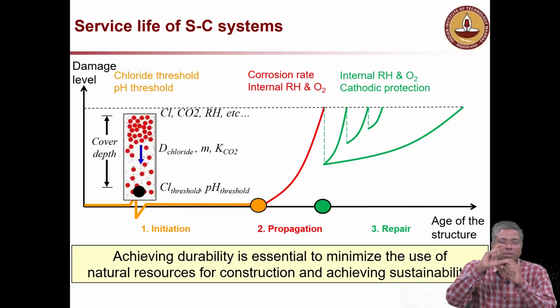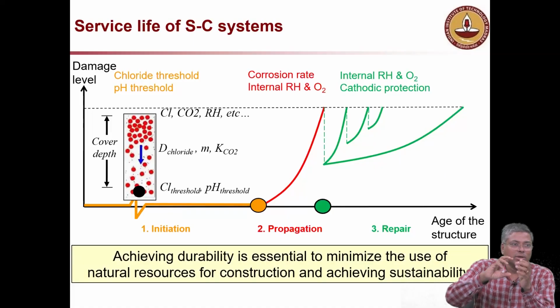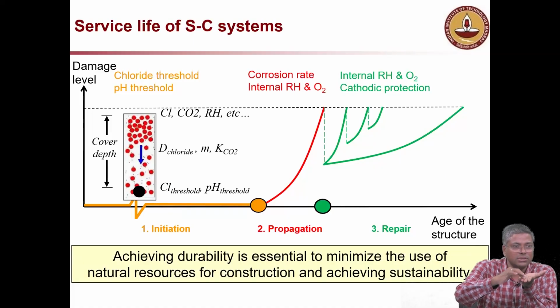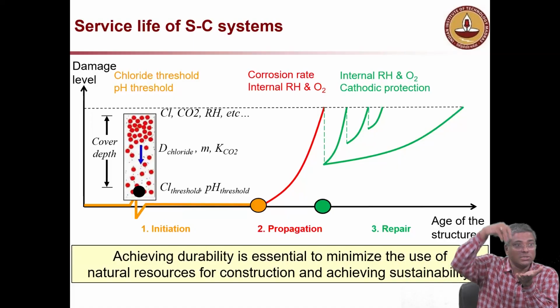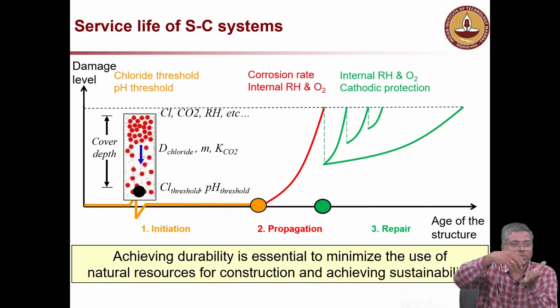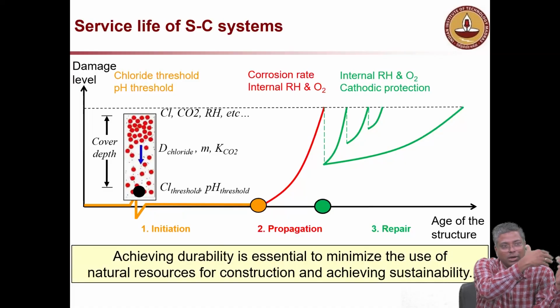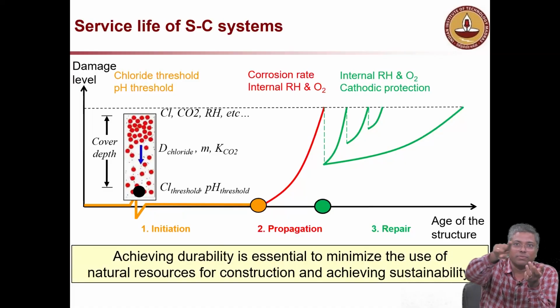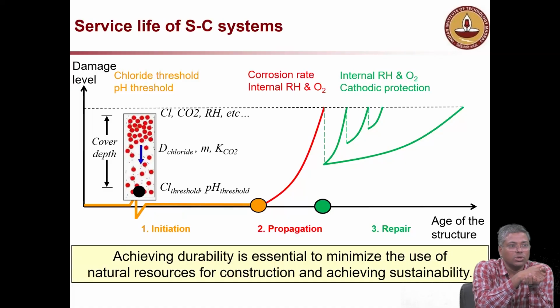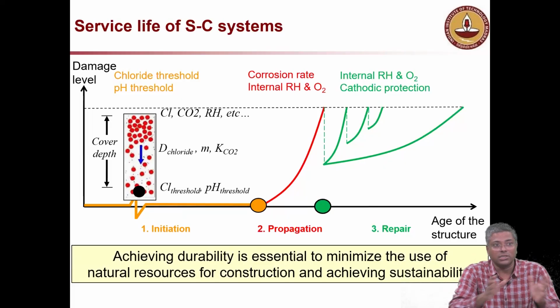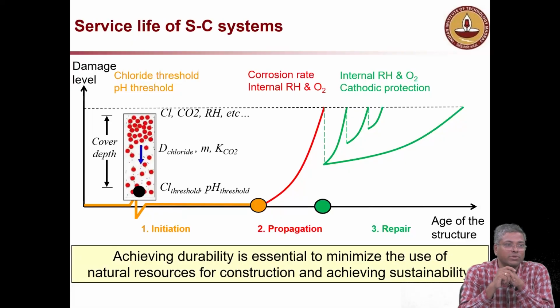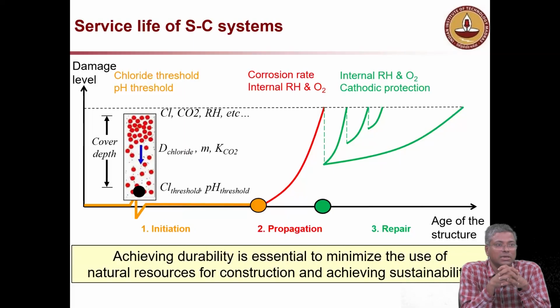See, the cover thickness is not like one parameter. You have to look at the travel distance, which is the cover. How much chloride is available outside? Let's say you're talking about seawater or some condition, that is another, the top surface chloride, CO2, RH, all those exposure conditions. Okay, travel length, and also the type of steel and concrete which you use. It's not only a parameter of concrete, it's also a parameter of steel and concrete, the resistivity of the concrete. All this plays a significant role.